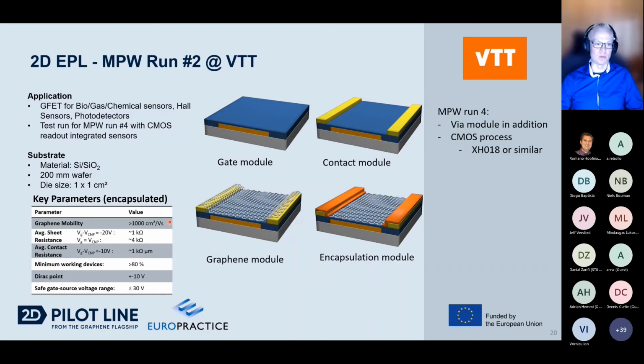The values that we are promising for these devices: graphene mobilities will be over 1000, and the sheet resistance values will be around 1 kilo ohm when further away from the Dirac peak, and around the Dirac peak region it will be around 4 kilo ohm. And then the average contact resistance values will be around 1 kilo ohm micrometer or less. The minimum working devices are 80%, and the Dirac point will be plus minus 10 volts, and the safe gate source voltage for the process that we are working with is plus minus 30 volts.